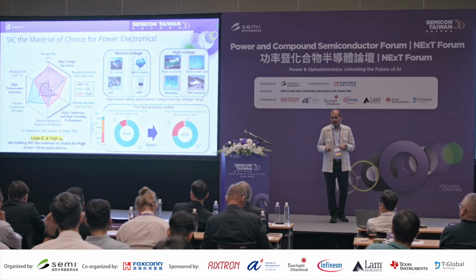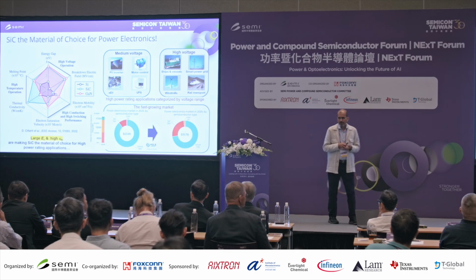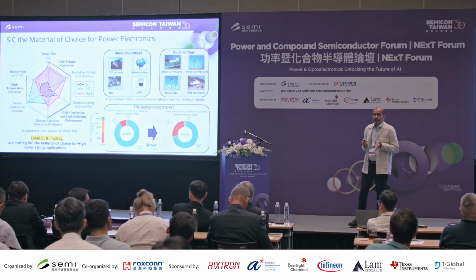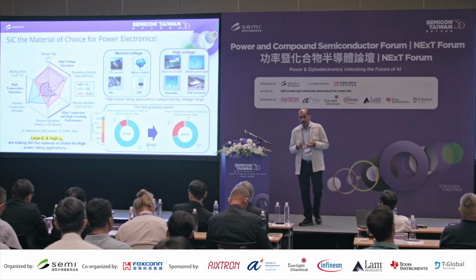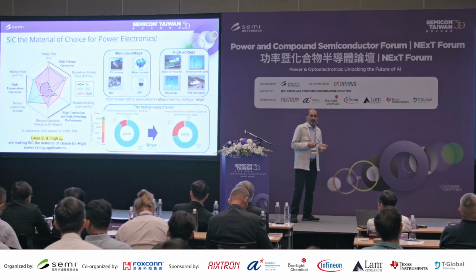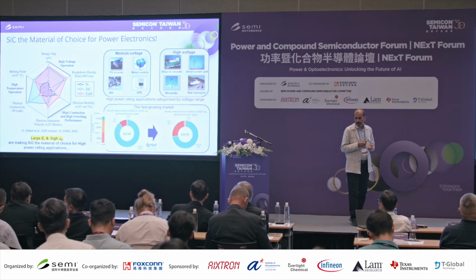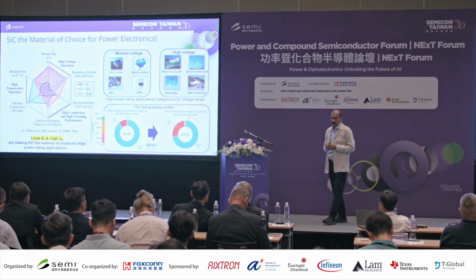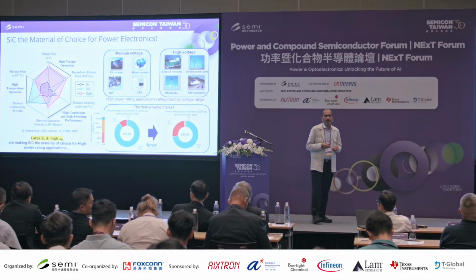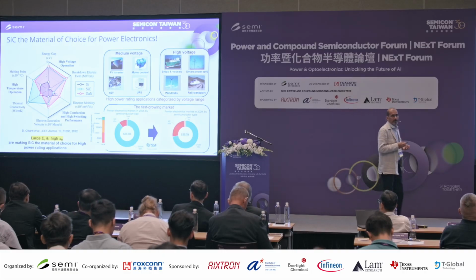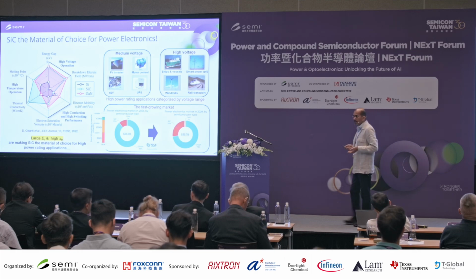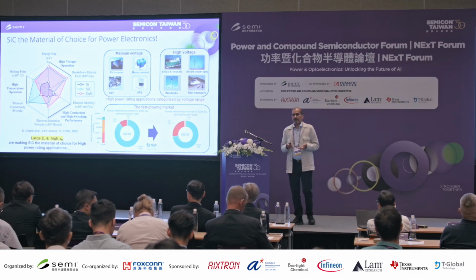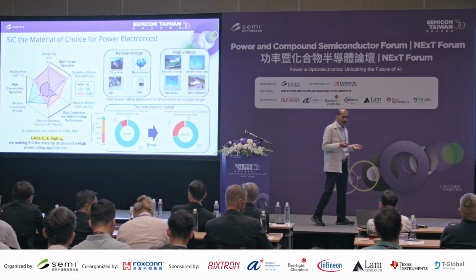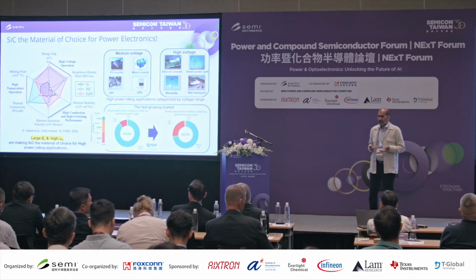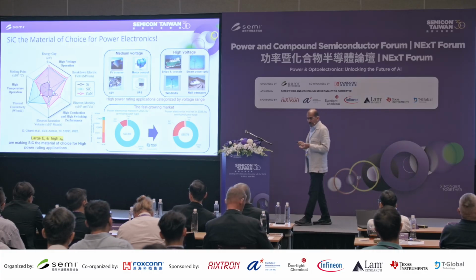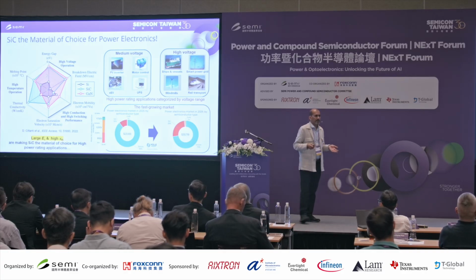Let me move into the material properties. If you look at on the left the spiral diagram, which tells the silicon carbide is a superior material. The most important property of the silicon carbide, which is making it a superior material for power electronics, is its breakdown field. Its breakdown field is about 10 times higher than silicon. That allows the drift layer in power device to be shrunk by 10x, and the doping level to be increased by at least 2 orders of magnitude, making almost 1,000 times improvement in drift layer resistance. There are other issues which need to be sorted out, but drift layer resistance can be very significantly reduced.